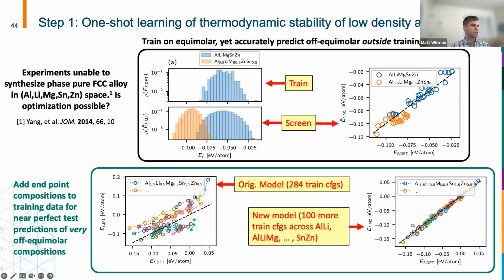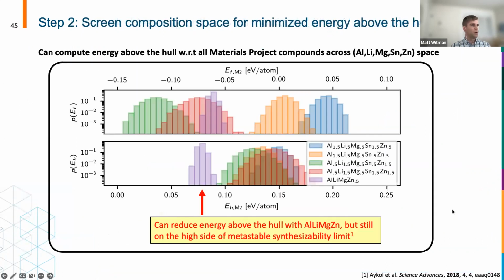You can really push that to the extreme. We're applying this original model to really off-equimolar compositions. And now qualitatively, each composition is well predicted. You can see that the slope of all these lines is pretty close to 1 for the model predictions versus DFT, but they're off by a constant shift. So in order to do this kind of one-shot learning, you just need to add a very small number of configurations across the endpoint compositions. And then that makes your ability to predict accurately at all these equimolar or off-equimolar ratios more or less perfect. So we can then screen across all of the composition space that we might want.